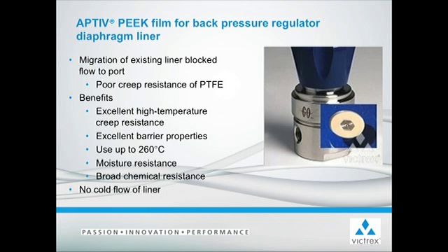This application uses our APTIV PEEK film as a diaphragm liner for a back pressure regulator. The problem with the PTFE material was migration of the existing liner, blocking the flow to the port, and that was due to the poor creep resistance of the PTFE. The APTIV PEEK film is acting as a backup seal for the PTFE diaphragm and provides excellent high temperature creep resistance, excellent barrier properties, the ability to use it up to 260 C, excellent moisture resistance, and broad chemical resistance. It also allows no cold flow of the liner in acting as a backup.